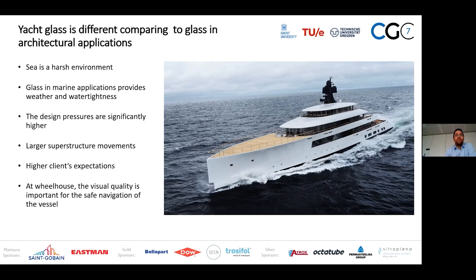Some of these are that the sea is obviously a harsh environment. In case of an emergency, it's very difficult for people to evacuate the vessel or for help to arrive quickly. Glass provides weather and water tightness, which prevents the vessel from capsizing or sinking. Also, pressures and superstructure movements are particularly high. A typical pressure is 15 kPa, and we can easily get more than 100 kPa in particular locations of the sea. The expectations of the client are even higher. And in some locations, the visual quality of the glass is important, not only for aesthetics but because, for example, at the bridge deck, it's necessary for the safe navigation of the vessel.